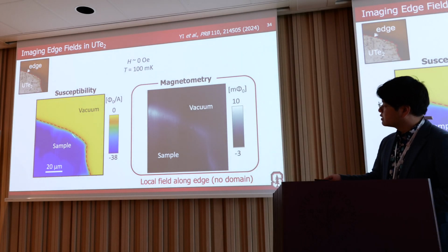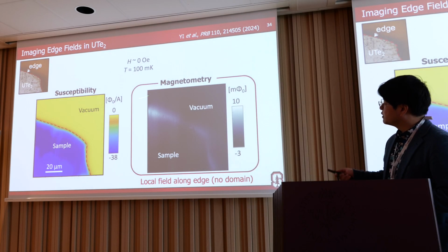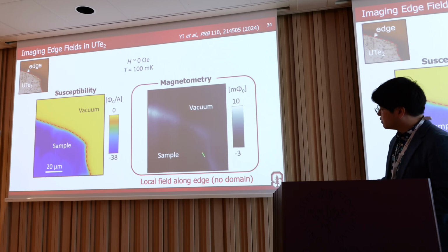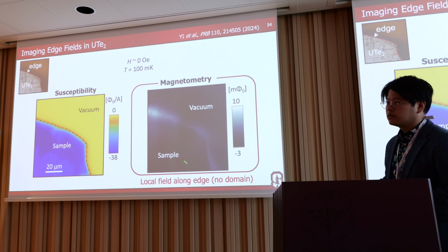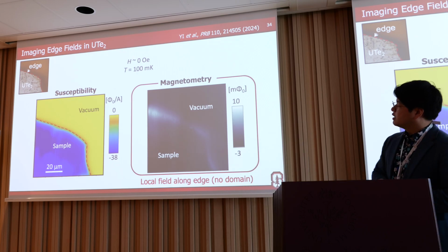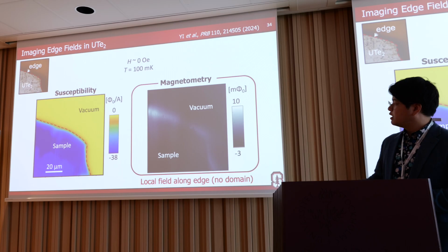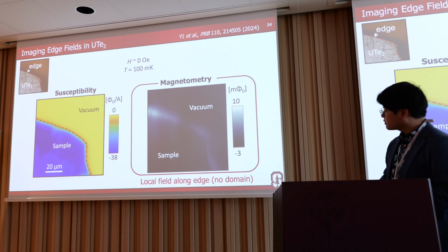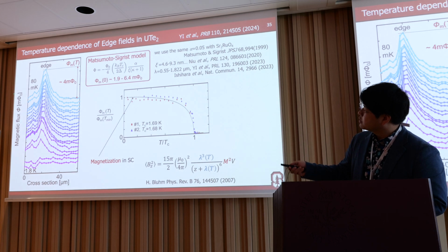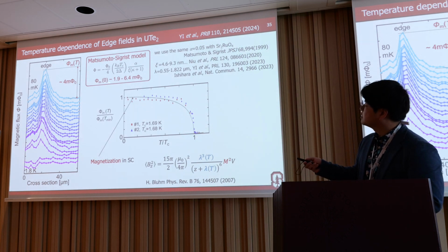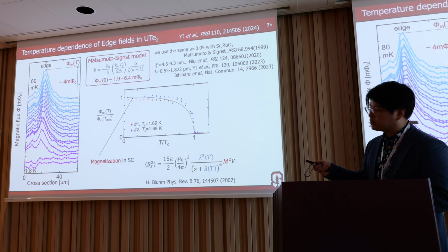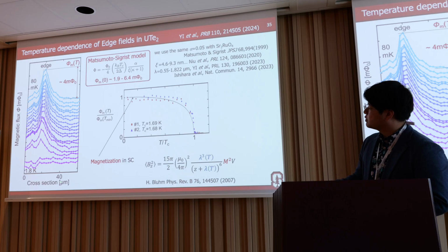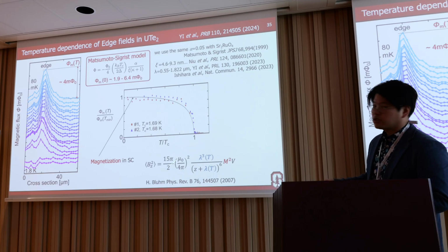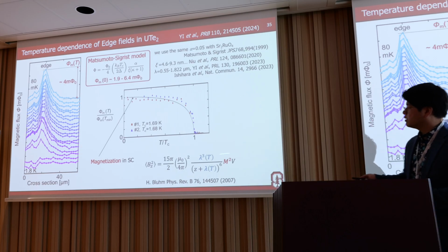So here I focus on the edge state in zero field cooling. We see the magnetic field as a peak structure along the edge over a 50 or 60 micron scale. This looks exactly like what we expect for the edge current, but it's much larger. This is the cross section of the magnetic flux, about 4 mΦ0, and this is consistent with the Matsumoto-Sigrist model. Then as we increase the temperature, this peak disappears just below TC. And this can be fit with the phenomenological theory of the magnetization in the superconductor.